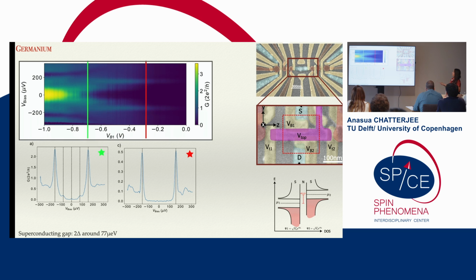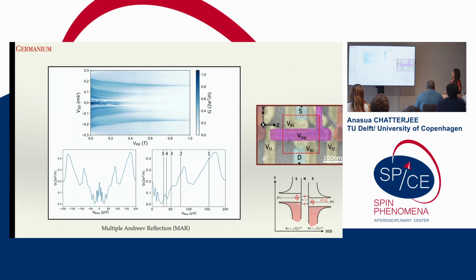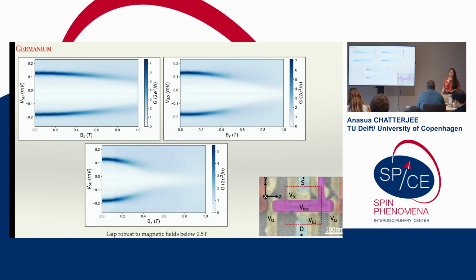But what's also nice is that if you look at the central part of the device, and we have a version with a top gate on top, then you can actually turn on a supercurrent and see these coherence peaks on the edge. So you can set up superconducting transport through this center patch. You can also set up multiple Andreev reflection, going up to, let's say, 5 peaks. And this gives you assurance that this is a somewhat transparent system. You don't etch the system, which is good, and you don't create disorder that way, but by annealing in, you're also hopefully not damaging it so much.